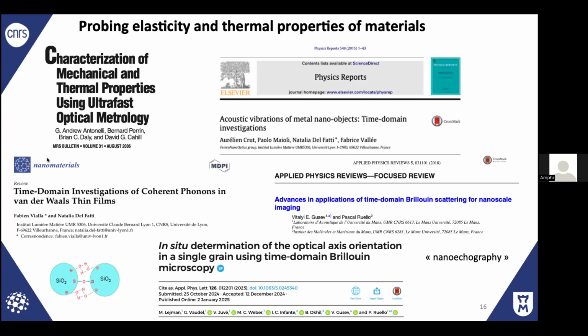And this is also what we can do. If you are able to make such a particle vibrate, you can probe directly van der Waals interaction. So this is typically what people are also doing now. Remember the picture I mentioned before: if you shine light, you make a nano-object vibrate. And if you look at the vibration on the surface, you can measure directly, finally, the van der Waals bond stiffness. So this is from the application point of view. You can also use phonons to make imaging, something I will not discuss today, but what we used to call nanoechography. It's basically the same idea as the echography that you know, but since you work with a high frequency, you can go down to very small spatial scale.